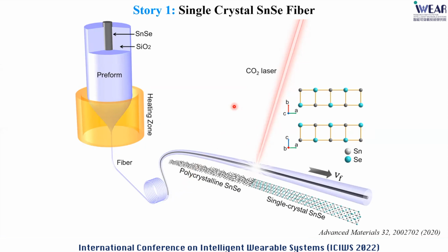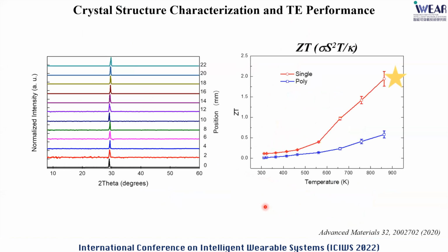So we developed this technology, so-called laser recrystallization. We used a CO2 laser here to further process the material, giving it directional heating and cooling. In this case, we can use the laser to guide the crystal growth inside the fiber. After the process, we are able to achieve single crystal tin selenide. After the fabrication, we used XRD to map the length of the fiber, and we see a single peak along the entire length of the fiber, indicating the single crystal nature. We also measured the thermoelectric performance between the single crystal and the polycrystal.